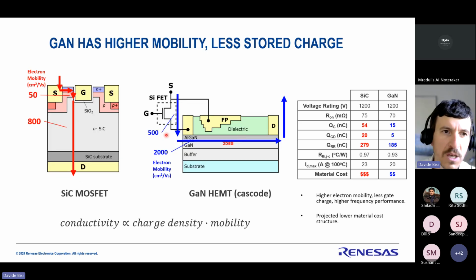Because of the higher mobility, the channel is 50 for silicon carbide and 800 for the drift region. In GaN, we have 2000 for the drift region. And even if you have a cascode configuration, the silicon FET mobility is 500, so it's already 10 times higher than silicon carbide. You know that the conductivity is a product of charge density times mobility. So if mobility is low, charge density has to be high. But if charge density is high, it means that capacitance is high.